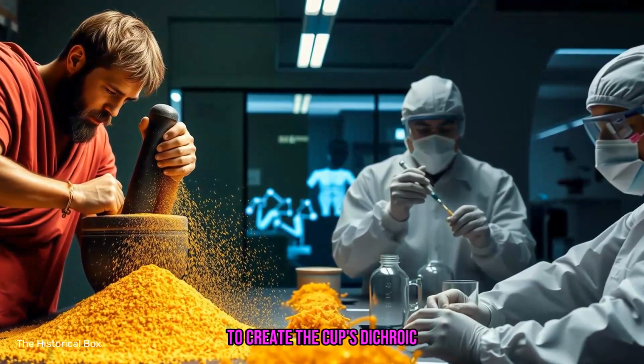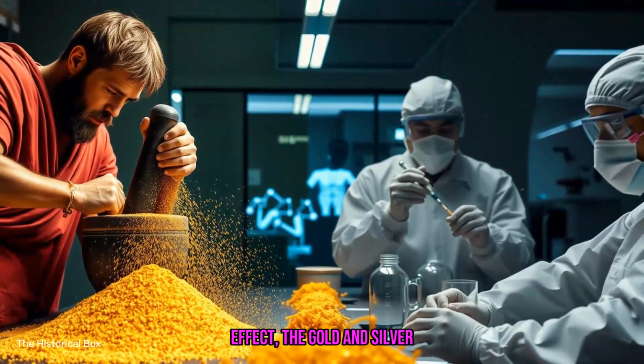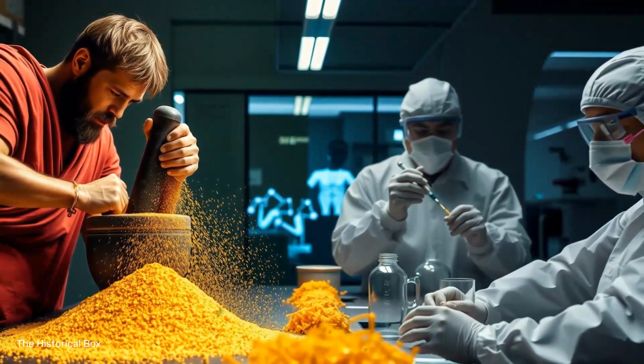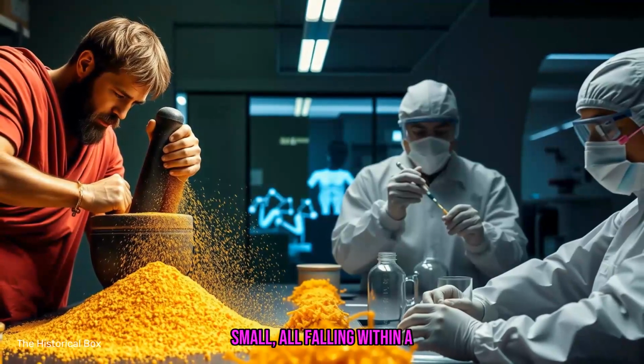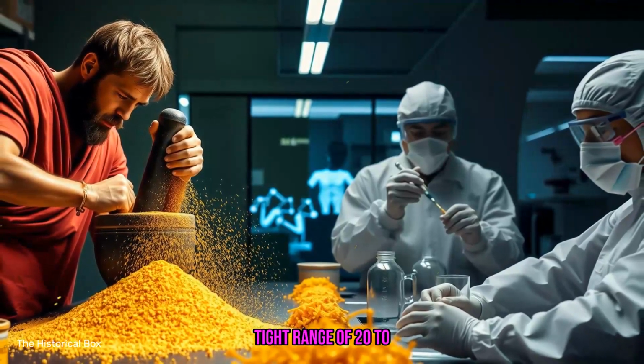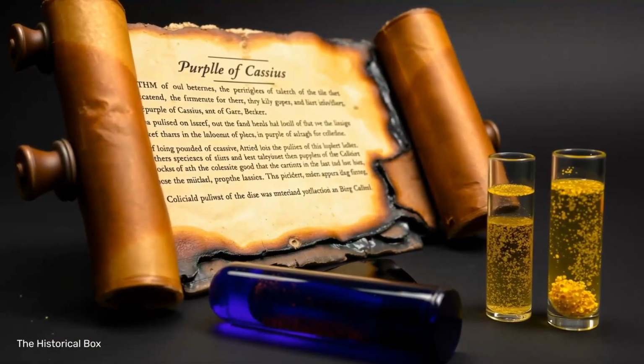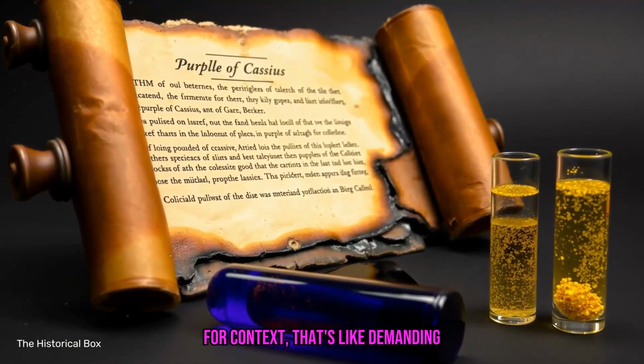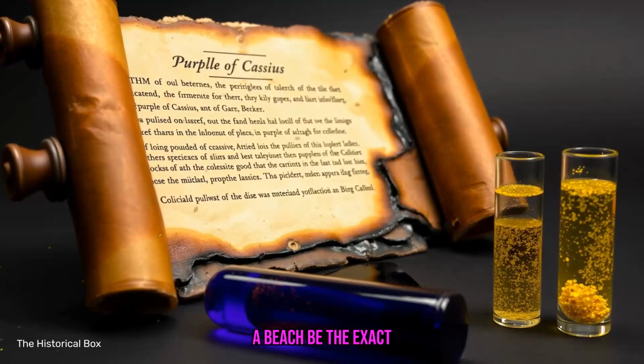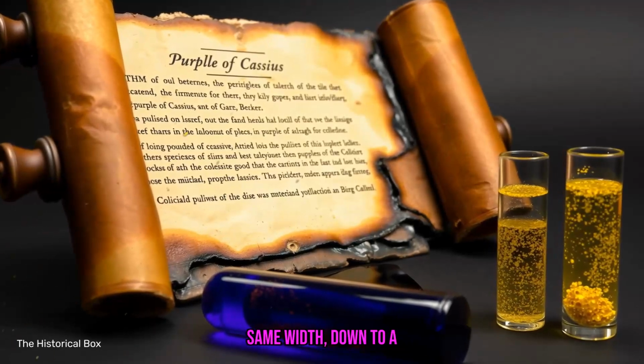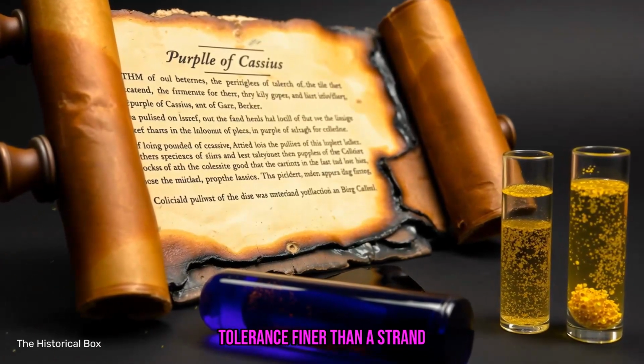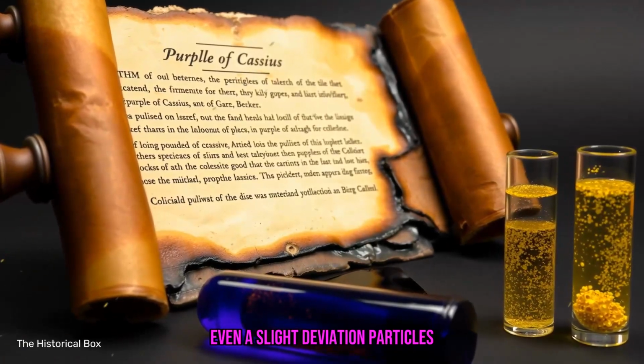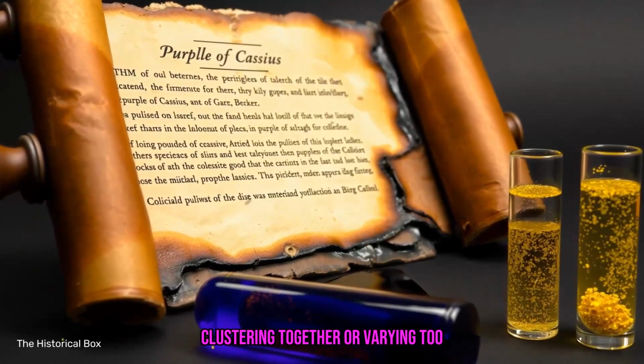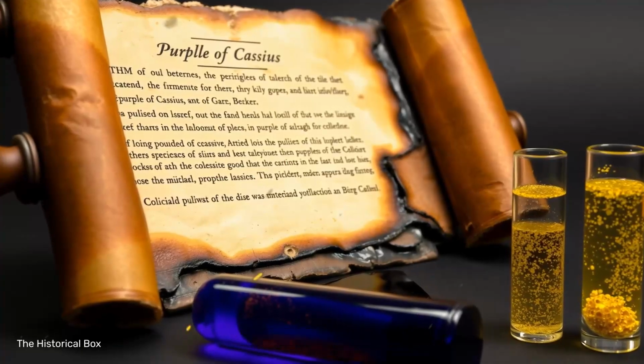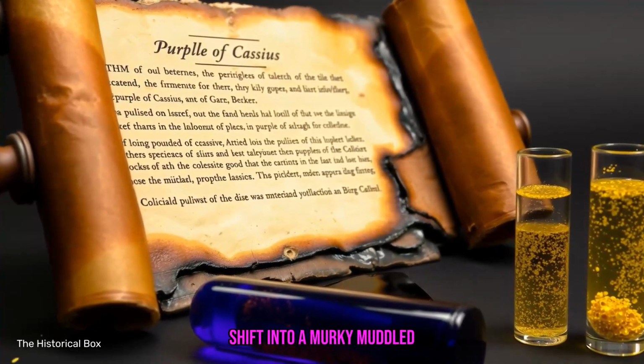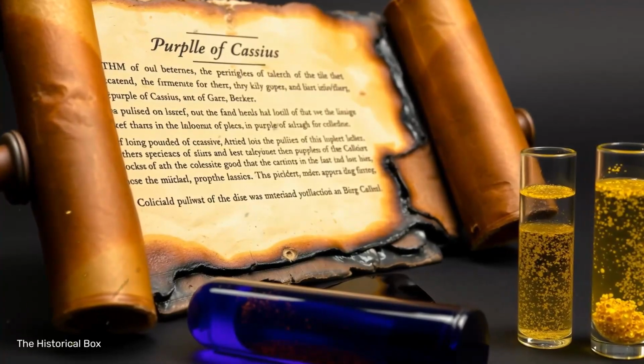To create the cup's dichroic effect, the gold and silver particles couldn't just be small. They had to be consistently small, all falling within a tight range of 20 to 50 nanometers. For context, that's like demanding every grain of sand on a beach be the exact same width, down to a tolerance finer than a strand of DNA. Even a slight deviation, particles clustering together or varying too much in size, would have turned the cup's vibrant color shift into a murky, muddled haze.